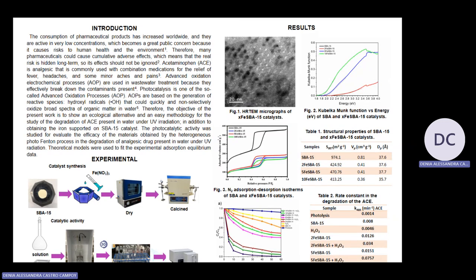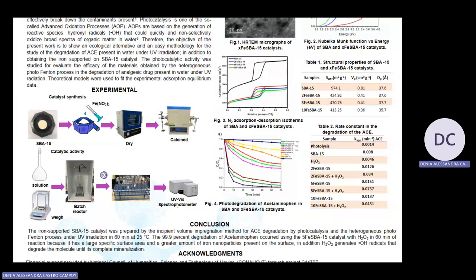Figure 4 shows the percentage of catalytic activity in the degradation of acetaminophen molecules using SBA-15 catalyst under UV radiation, where concentration is plotted against time over initial concentration. It is observed that the concentration decreases by 99% at 16 minutes of reaction. Table 2 shows an adjustment to a first-order kinetic model, where the natural log of initial concentration over concentration at a given time is plotted, giving a rate constant for 5%-iron SBA-15 of 0.0757 min⁻¹.